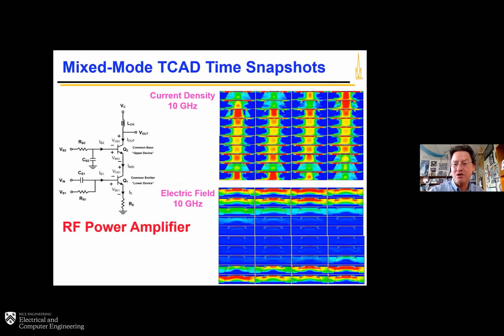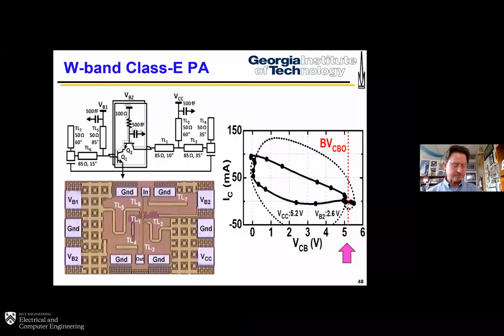But if you look at the lower right, you see whole regions of operation where not much is going on. Blue is good in this case, right? And so that led us to believe that we could play some games with biasing beyond what a PDK might actually tell you is doable. And so we built a W-band PA. You'll notice on the right-hand side that we're swinging above the BVCBO of the device, which is classically nobody in their right mind would do, but you can actually get away with that.